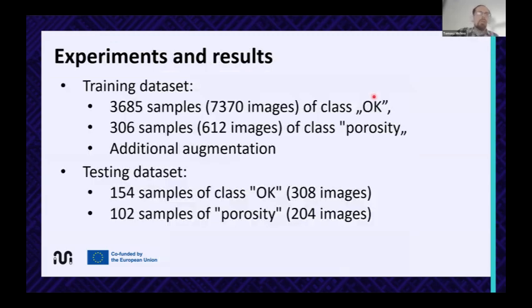And for the experiments, we used a lot of images for the training. Because we used both images for one part, we had more than 3,500 samples, which is 7,370 images of class OK, so good part. And because during the process, it's not so easy if it's a real working factory. It's not easy to gather a lot of bad samples because this is not the main aim of the real production. So we have only 612 images of porosity class.